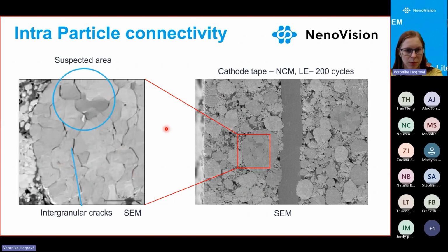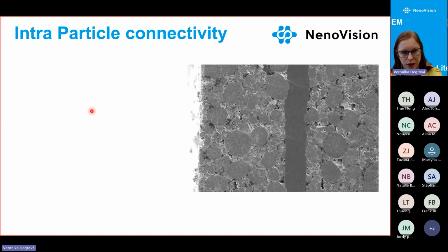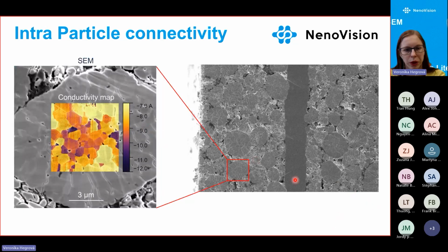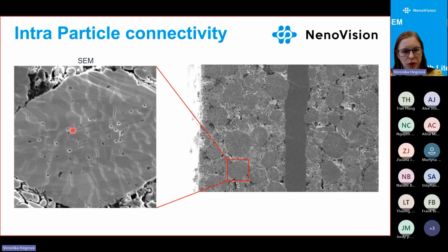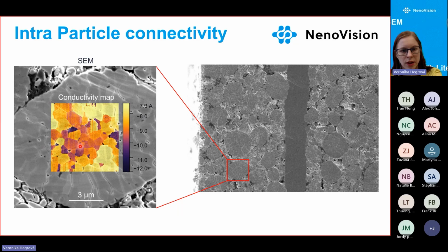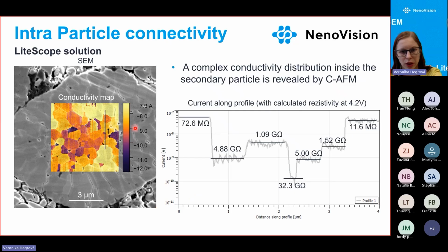And there is a suspected area, for instance, because the material contrast is quite different. And so what we did, we chose the particle and measured the conductivity. And as we can see, there are already in the SEM image parts of cracks. And when we measure the conductivity, we see that some of the grains are completely turned off. And if we make a line, we can see that the current along the profile, the numbers are quite high. So it shows us a complex conductivity distribution inside of the secondary particle.